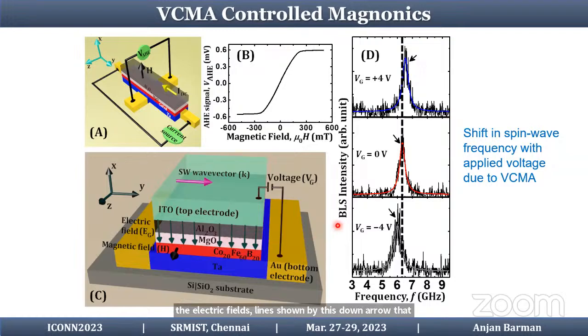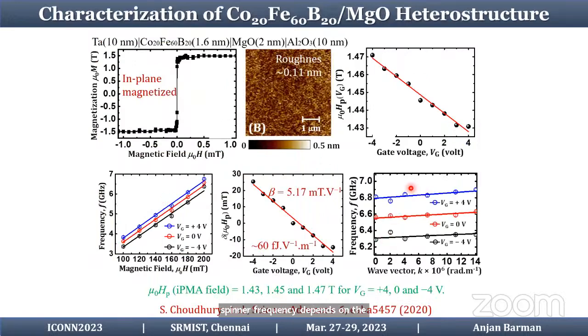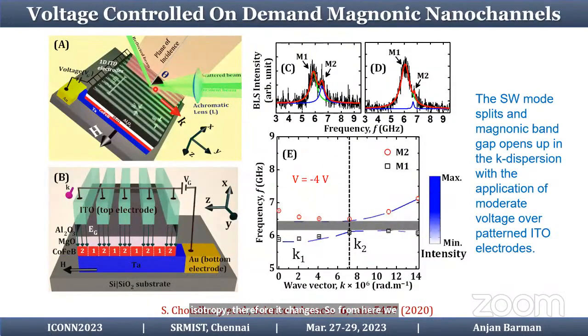So you can see the electric field lines shown by this down arrow that modulates the interface, and that gives rise to the VCMA. So we measure the spin waves for this uniform mode, and we can see there is a single mode whose value shifts as a function of this voltage, because of the change in the magnetic anisotropy, and since spin wave frequency depends on the anisotropy, it changes. So from here we characterize various things like the VCMA constant and so on.